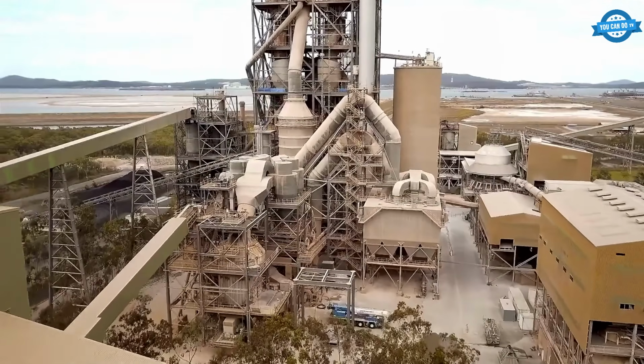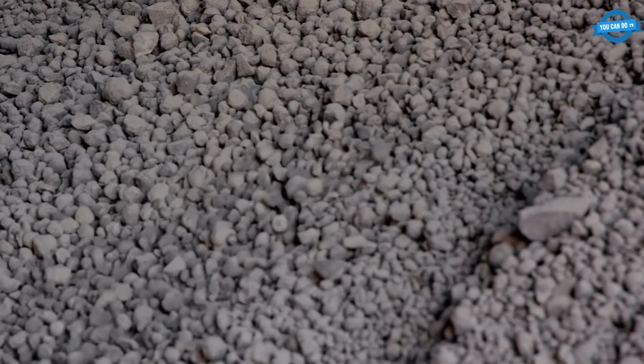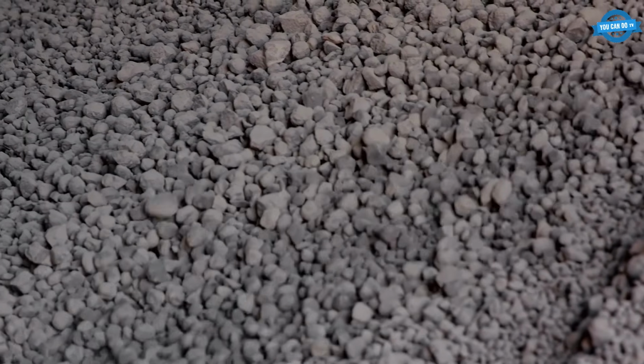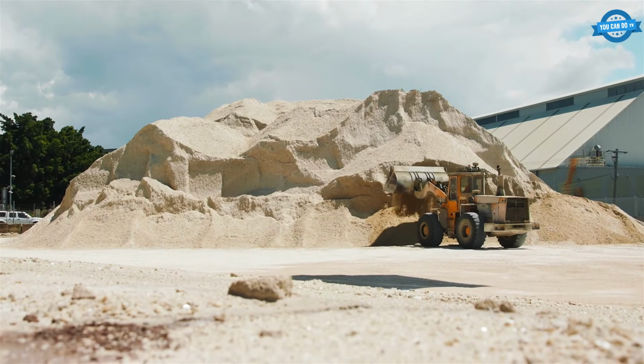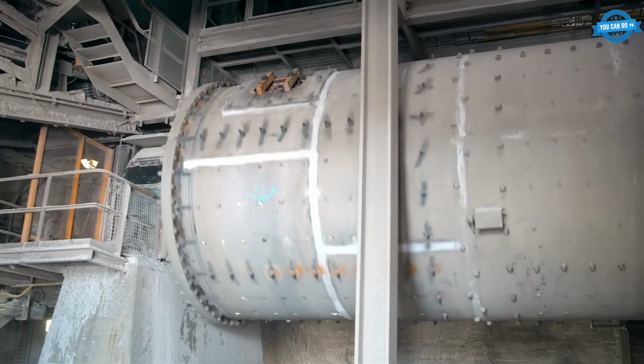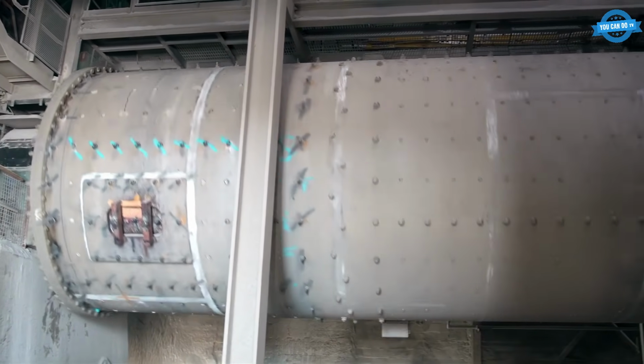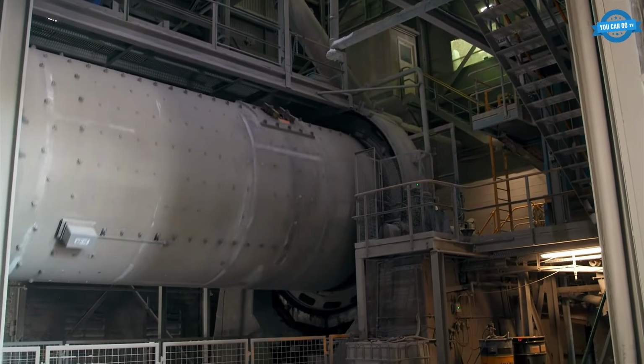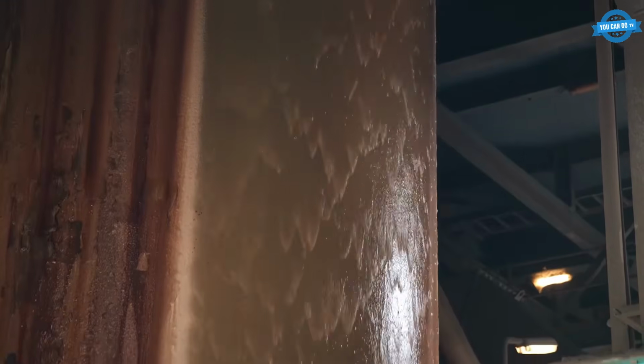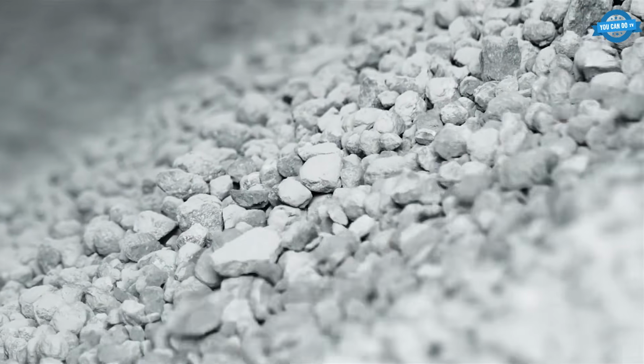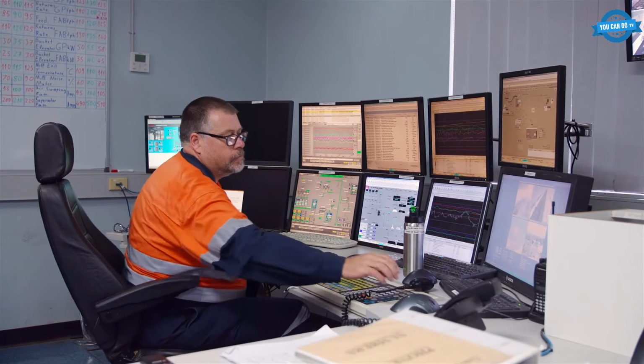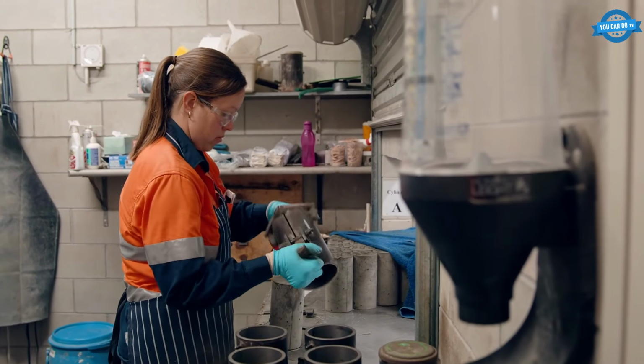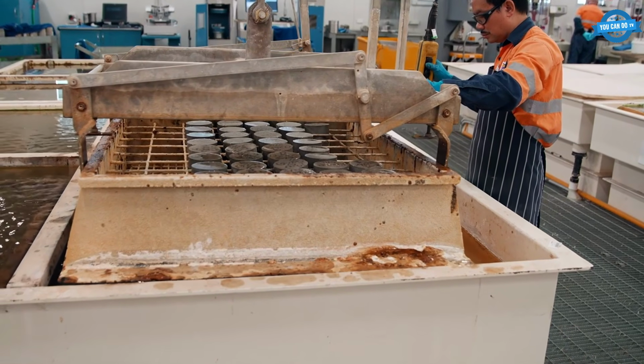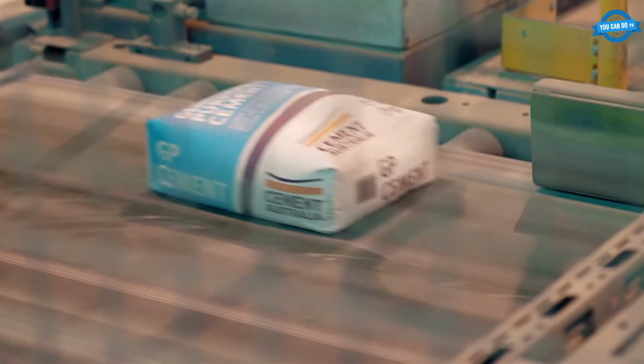Carbon dioxide escapes. What comes out the other end is a hard, glassy pellet called clinker, dark gray, almost metallic, and nothing like the pale rock that went in. Clinker cools on a grate, then gets ground with a small amount of gypsum inside enormous ball mills and vertical roller mills. Only now does the powder deserve the word cement. Lab crews test every batch, curing test cubes in water baths for weeks to prove the mix meets strength targets before a bag ever ships.